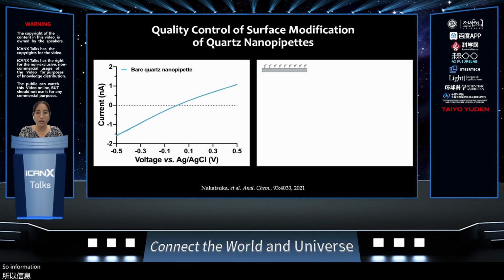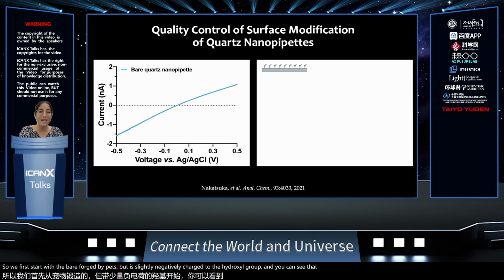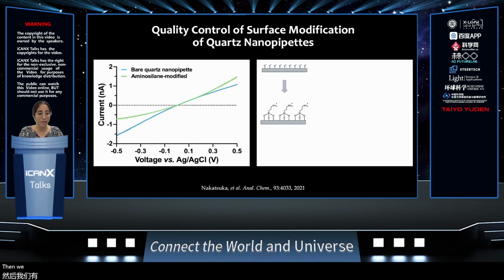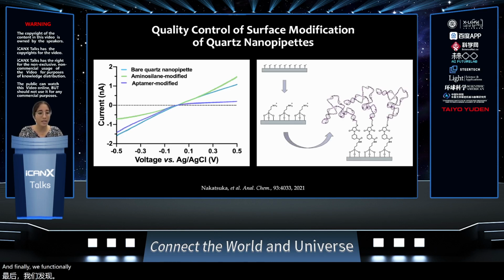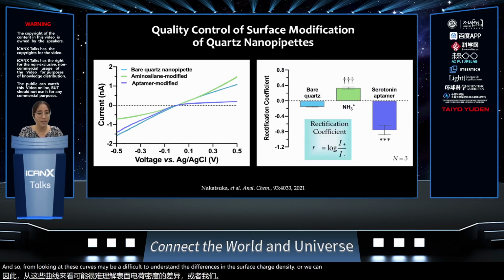So we first start with the bare quartz pipette that is slightly negatively charged due to the hydroxyl group, and you can see that it's slightly nonlinear in the behavior. Then we assemble aminosilanes through vapor phase chemistry in order to create a monolayer. And finally, we functionalize the DNA aptamers that are highly negatively charged. And so from looking at these curves, maybe it's difficult to understand the differences in the surface charge density, but we can quantify this through a value called the rectification coefficient.